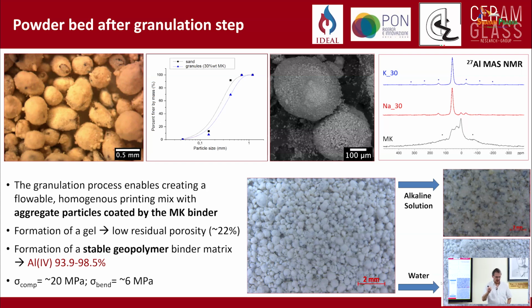So certainly you should ask, how can you form a geopolymer so quickly? Typically, in order to make a geopolymer, you work with it like it was Portland cement. So you mix it with water or with alkaline solution. You mix it thoroughly, and then you have dissolution and condensation reactions occurring. Well, we found out that actually the geopolymerization reaction is very, very quick, because simply dripping the alkaline solution on the coated granules leads to the formation of the geopolymer.